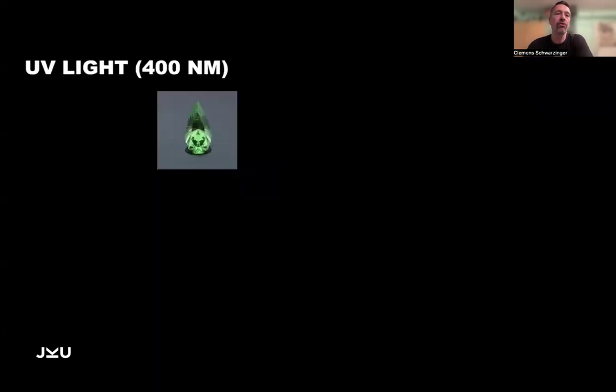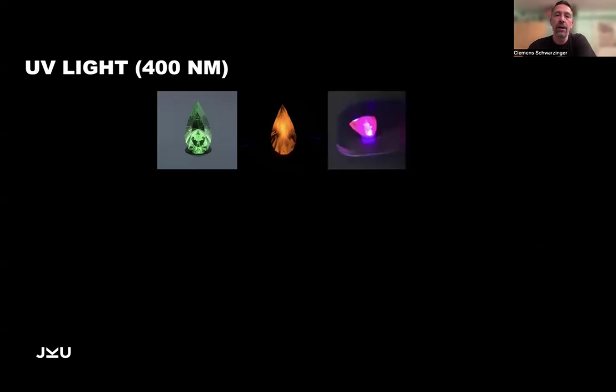And again, something that should be found in every gemologist's briefcase, I would say, or backpack, is a UV torch. The UV torch that I'm using here is 400 nanometers, or you can also use the 366. This is pretty much the same. And we have here a nice Merelani mint garnet or a bright green tsavorite, whatever you prefer. I use my torch and it shines a wonderful orange. I had another one, approximately the same color, same green. And you see here the fluorescence is pinkish to red.